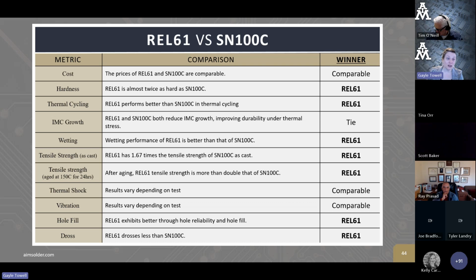REL61 is harder, performs a little bit better in thermal cycling. Intermetallic growth can be somewhat similar. Wetting performance, REL61's better. On tensile strength, after aging, it was better. Thermal shock and vibration can be somewhat similar between these two, but REL61 then does better with hole fill and also with drossing. So even compared to SN100C, which is a similar price point, you're still getting better performance across a lot of these metrics.